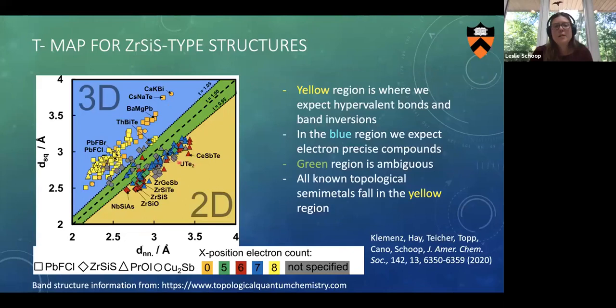And this material now has been studied extensively as a potential correlated topological material. So that means that unlike band structure calculation, where correlations give us a problem, these chemical distance rules seem to be immune to the problem of correlations. So that was great. But when we just looked at this structure type, which is isostructural to zirconium silicon sulfide, we did not find any new interesting materials to study in this area.